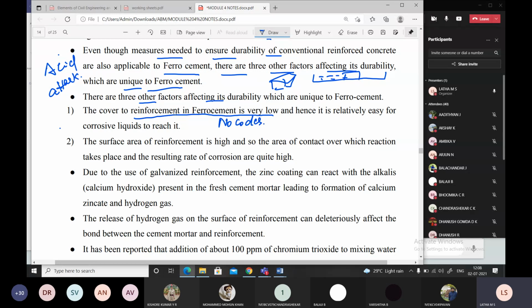So the cover of reinforcement in ferrocement is very, very low. Like in RCC, you find 25 mm, 55 mm also, 65 also it goes for fire resistance, and hence it is relatively easy for corrosive liquids to reach. Yes, acceptable. It is easily corroded. The surface area of reinforcement is high, and so the area of contact over which reaction takes place, resulting in corrosion, is very high.